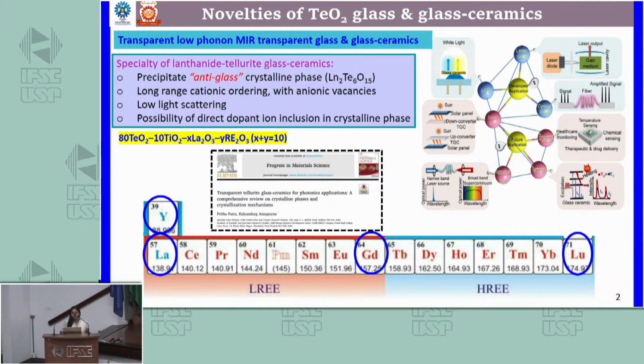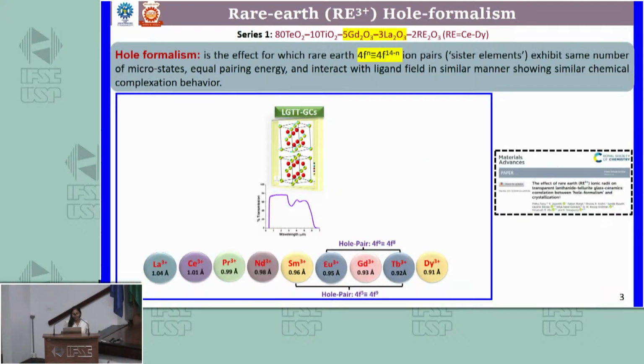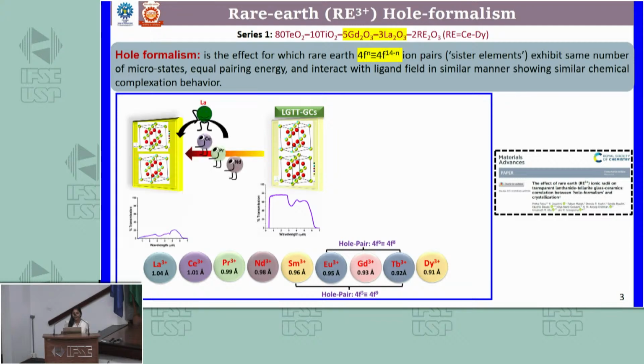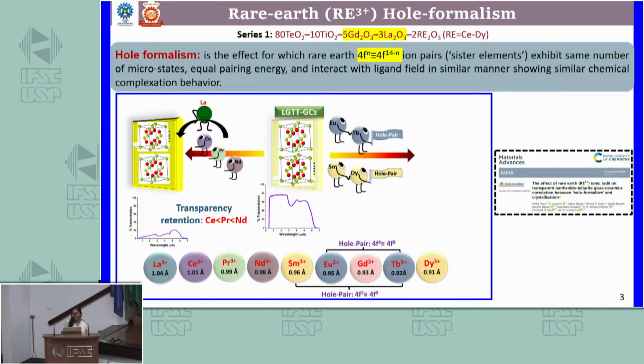Out of all the tellurite glassy matrices, I particularly chose to work with the lanthanide tellurite matrix. We have doped more than half of the rare earth series, from cerium to dysprosium, and checked the effect of different rare earth ionic radii on the crystallization mechanism and transparency retention of the glass ceramics. Here we came up with a very interesting fact: rare earth pairs with electronic configurations of 4f^n and 4f^(14-n) exhibit the identical crystallization mechanism as well as the same transparency retention.